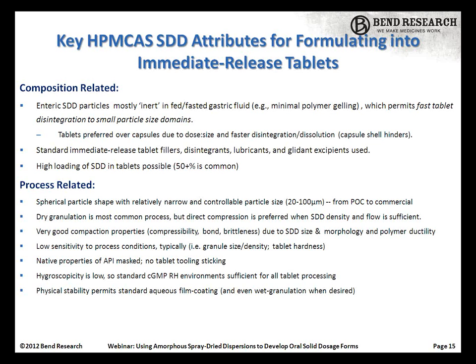Again, we use very conventional fillers, disintegrants, lubricants. We can get high loading. We very commonly are at 50%. I would say up to 70% is within our working range. 70% and below, and 50% and below is very straightforward. On the process side, the particles are spherical relative to crystalline API, which of course is all over the board on morphology and size. The size here is always going to be relatively spherical, with a relatively narrow particle size distribution. They're not aggregated.